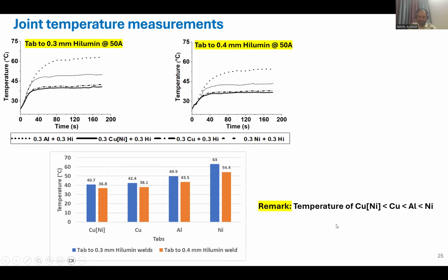So a similar trend is obtained here as well, like resistance. You have the lowest temperature rise for the nickel plated copper and maximum for the nickel, because this is just a reflection of the resistance. The more the resistance, the more the temperature rise. So that's why you have got the same trend here for temperature as well.